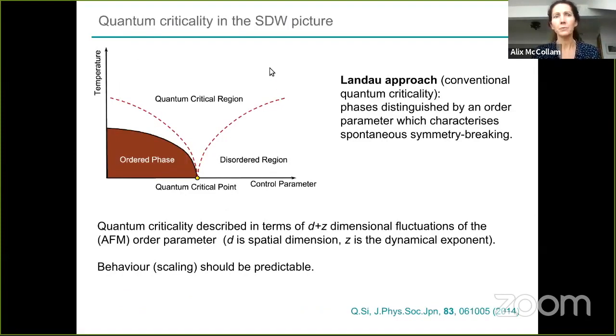Okay, to summarize the two pictures, there are people probably listening that are better qualified than me to talk about this. But this is the spin density wave picture. So this is a rather conventional phase transition. So on our canonical Doniach phase diagram, this is the type of continuous second order, probably, phase transition that you would have. So it's a conventional quantum critical point. The phases are distinguished by the development of an order parameter in the ordered phase and spontaneous symmetry breaking on this side. There are fluctuations that you can describe and predict associated with the development of the order parameter. So this is a conventional phase transition.